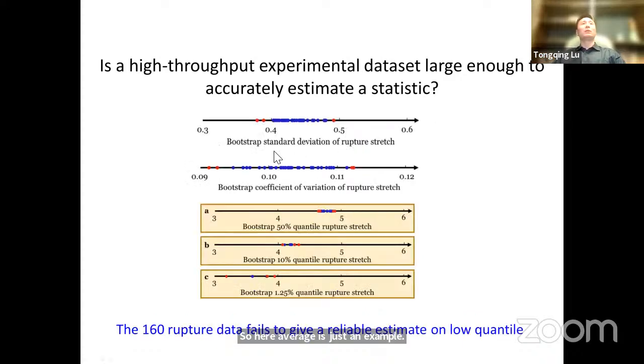So that's the idea. The bootstrap analysis can quantify the size of the experimental data set required for an accurate estimate of any statistic. Here, average is just an example. For other statistics, for example standard deviation or coefficient of variation, we can do similar things. For quantiles, we use the bootstrap method to determine the confidence interval for the 50% quantile, 10% quantile, and 1.25% quantile. We can see with the 160 rupture data, the predicted 50% quantile has a very good, accurate confidence interval.